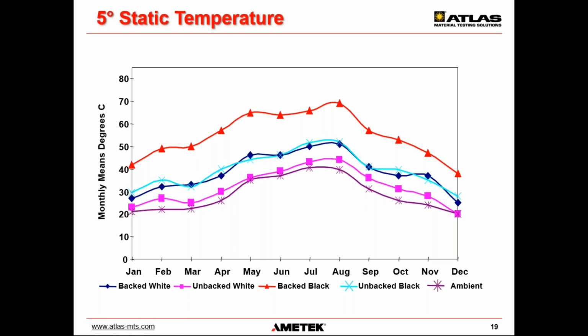What I want to note, first of all, you'll see here that a backed black sample is always going to be much, much higher than anything else, absorbs a lot of solar radiation, and it's in this backed configuration. But what I think is kind of interesting here is note the dark blue diamonds and the turquoise colored X's that you see right here that pretty much almost mirror one another throughout the course of the year. Well, one of these is an unbacked black material, and the other is a backed white material. So we have basically turned this white material black, in terms of its temperature profile, just simply by backing it. So as you see, the temperatures are almost the same between a backed white material and an unbacked black material.